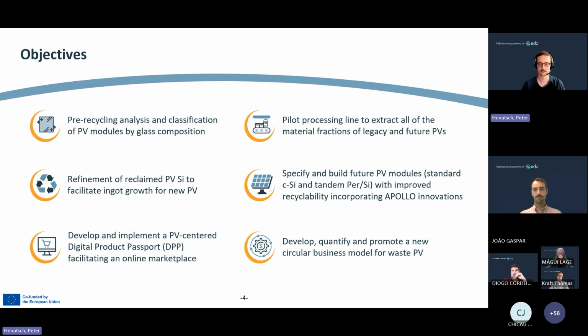So the second objective is to produce a pilot processing line to extract all of the material fractions of the PVs. So really address all of the fractions like silicon, silver, aluminum frame, glass, polymers, and so on. Then this recovered silicon has to be further purified. There our colleagues from Norway, from SINTEF and NTNU come into play. They have the thermal process to purify the silicon to a stage where we can use it for new ingot growth and for new PV.